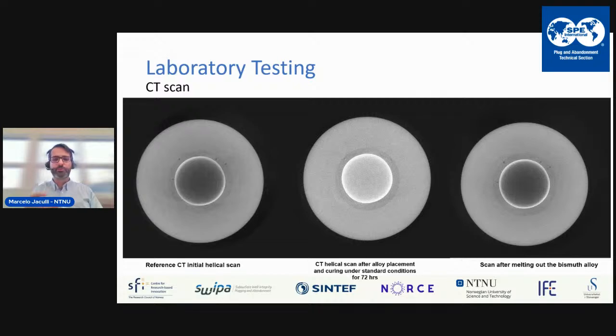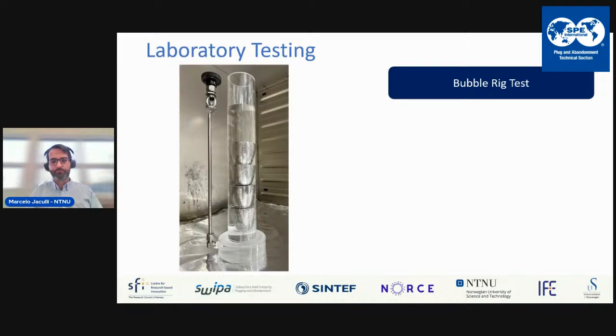So I said, okay, let's try to remove the plug and see the after effects. Then you can still see that some of the cracks were there, but some of them disappeared. We said we're not entirely sure what's happening here, if these cracks were really closed, or maybe the CT scan is not the best approach here. But this is something that definitely deserves more investigation.